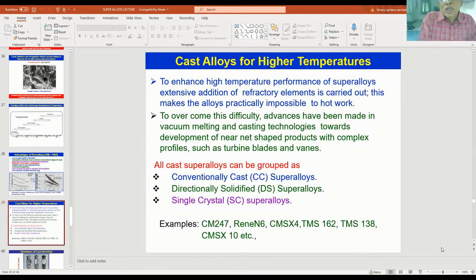Generally, cast superalloys cannot be forged and so on, but cast superalloys can be used at higher temperatures than that of wrought superalloys. We have a large number of refractory elements in the superalloys. Because of that, the refractory elements have high melting points, and then we have to work at very high temperatures. Hot working has to be done. It is practically impossible. To overcome this difficulty, advances have been made in vacuum melting and casting technologies towards development of near net shaped products with complex profiles such as turbine blades and vanes.